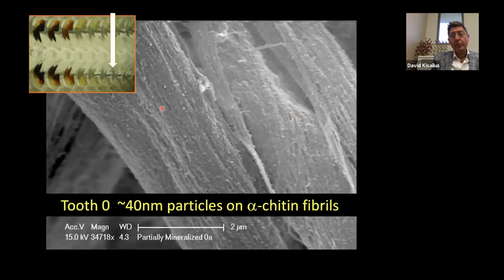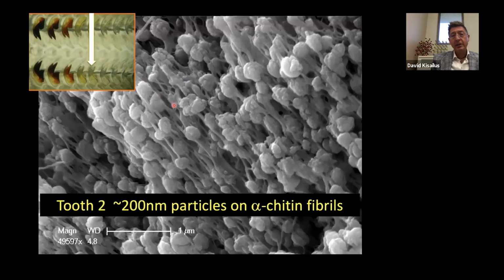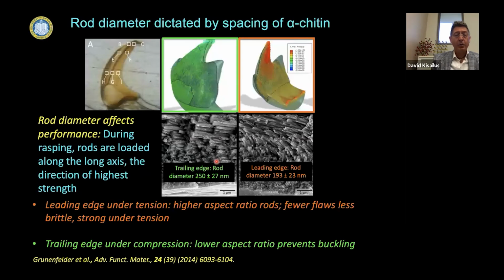So when you look at the first tooth, we call it tooth 0 because it's the first tooth that shows any color. We see these ferrihydrite particles, these small little domains here, forming on these alpha chitin fibrils, these long oriented fibers. And if we jump forward from tooth 0, where nucleation of mineral first forms, to teeth later, you can actually see the ferrihydrite has grown significantly, but guided by these scaffolds, these organic scaffolds, these alpha chitin structures. And so this is work again with our collaborator Pablo.